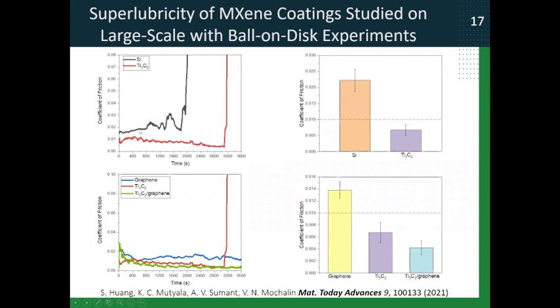So here is the coefficient of friction for bare silicon without MXene. And here is what happens when we deposit a thin layer of titanium carbide Ti3C2 MXene on that silicon wafer and test it. You see that when we deposit MXene on silicon, the coefficient of friction after initial run-in drops below 0.01 and stays at that value for the whole duration of testing until the coating eventually fails here at around 3000 seconds in this case.